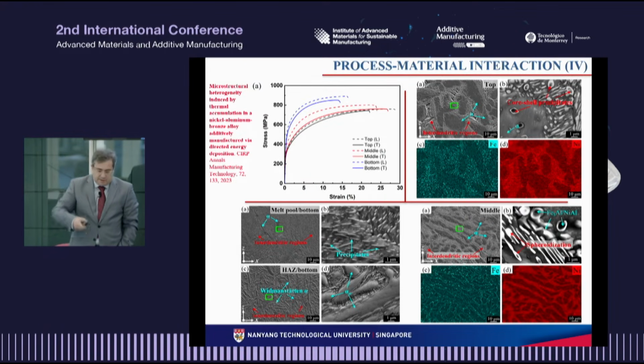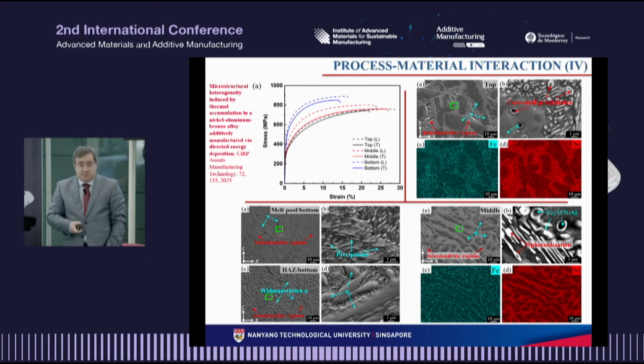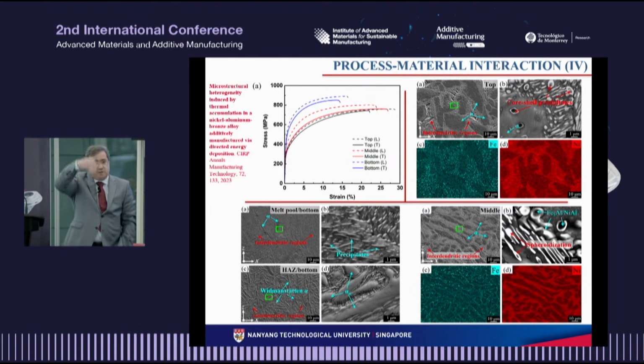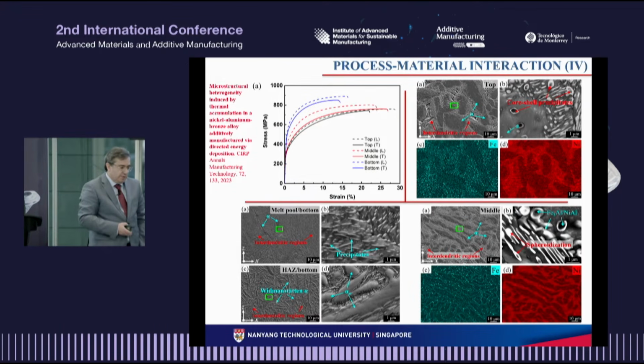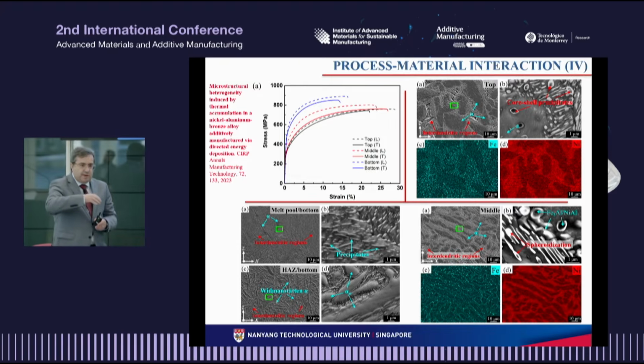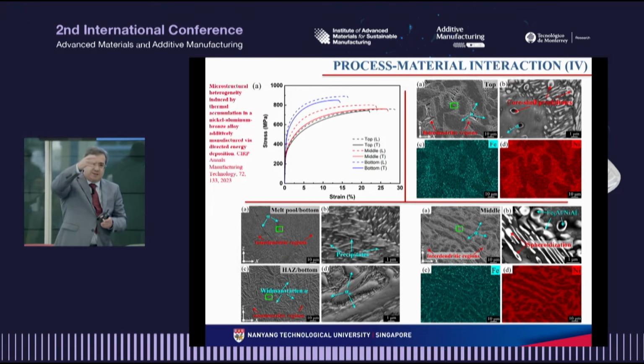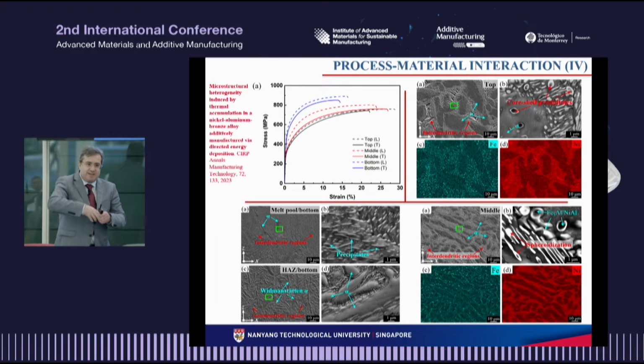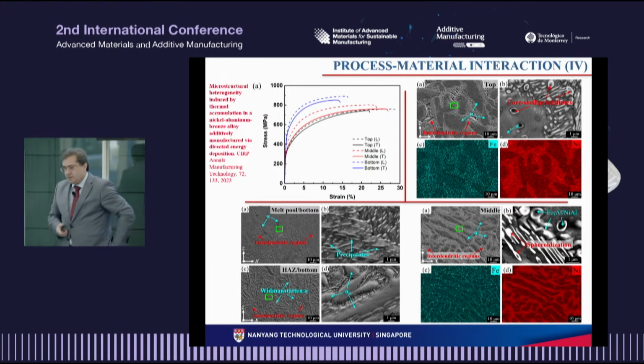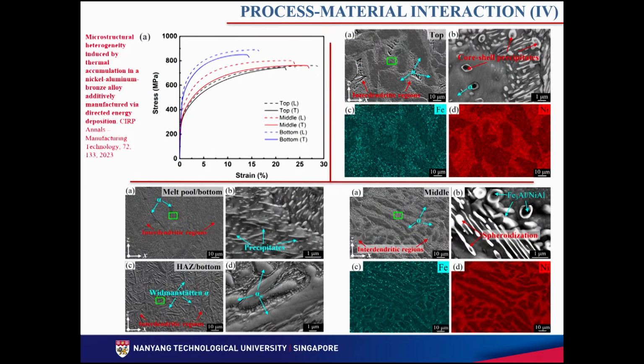the results show, as expected, a heterogeneous microstructure from the top to the bottom, with consequences in terms of the mechanical properties. And this was essentially due to the dominant effect of conduction in the cooling process. And as we move the melt pool from the substrate, the conduction effect becomes less effective. So in the paper, we discuss also strategies to control the input energy or using other external sources in order to allow a better control on the microstructure and on the mechanical properties of the parts.